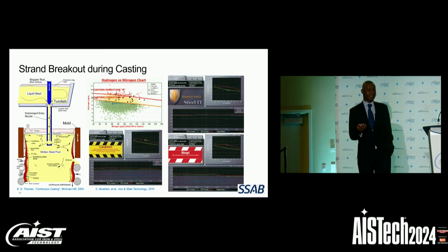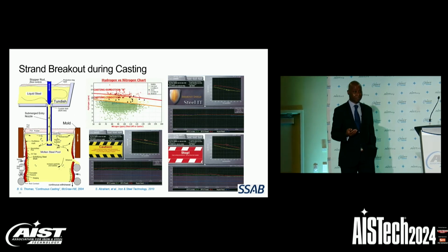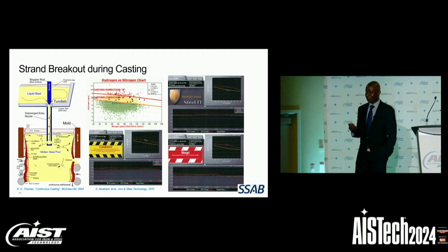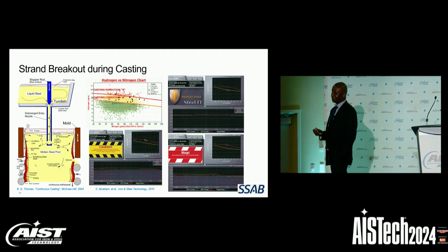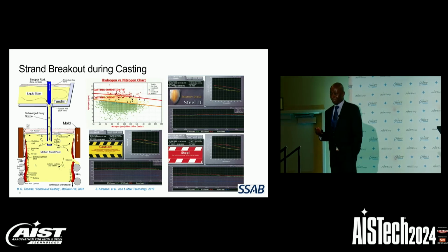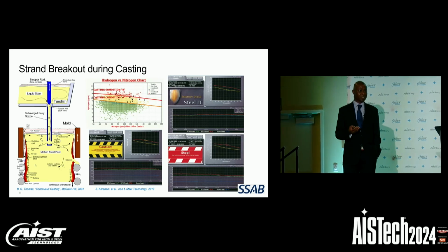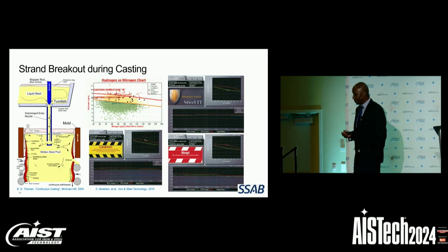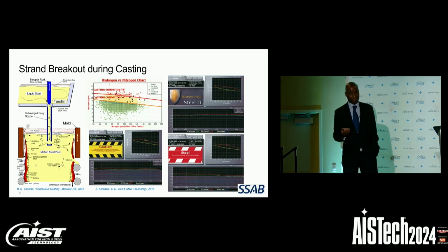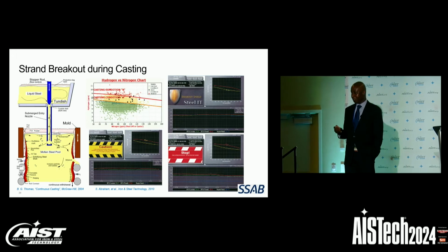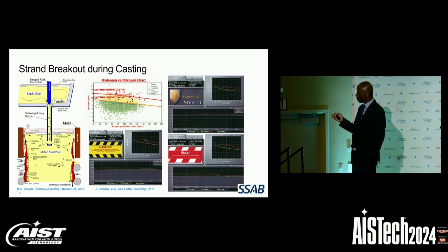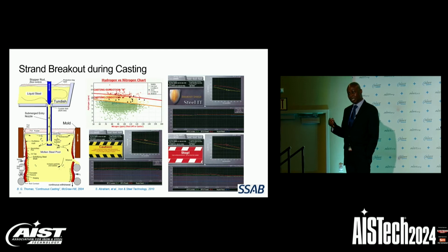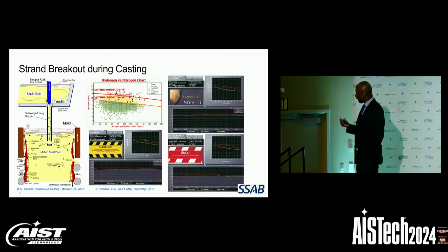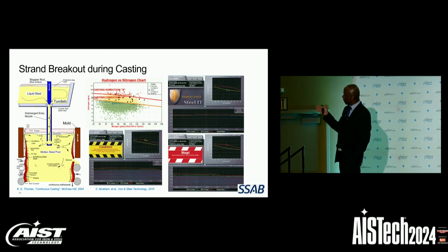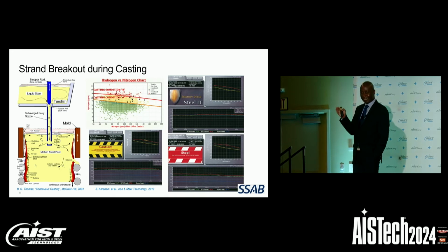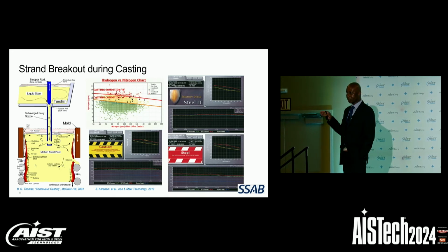So of everything that can happen during the continuous casting, none is more devastating than strand breakouts. There are many reasons why strand breakouts occur, but the one I want to focus on is the hydrogen-nitrogen-related strand breakout. So during solidification, the solubility of hydrogen and nitrogen decreases. So as the shell is solidifying in the mold, we have molecules of hydrogen and nitrogen that are coming out of the shell. And they can be trapped in between the shell and the mold wall, decreasing the heat transfer from the shell onto the mold wall.